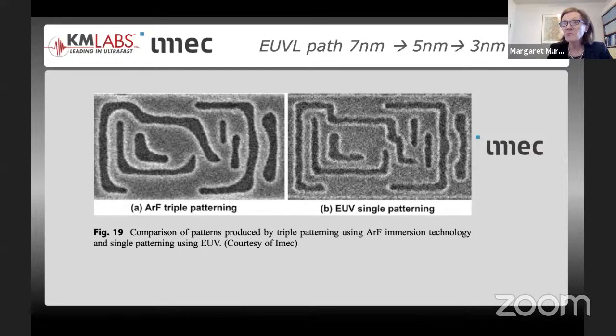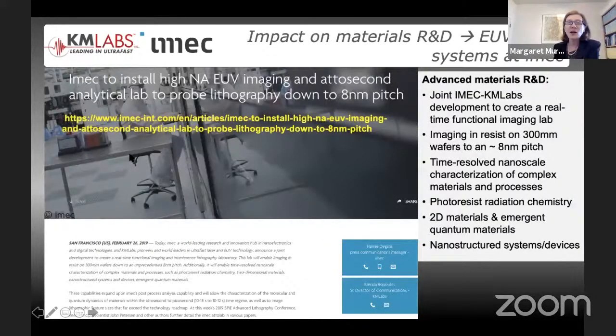So they'd like to develop better photoresist that might smooth these absorptions better, for example, and generate sharper line edge roughnesses. But the models for the photoresist that they've developed for UV don't work well in the EUV. So they have to go back and really ask, what happens when an EUV photon strikes a photoresist? What changes can I make chemically to spread that bond breaking more uniformly? And so a couple of years ago, IMEC decided to install a couple of these harmonic systems to create a real-time functional imaging lab to develop photoresist, but also to look at 2D materials and nanostructured systems and devices.